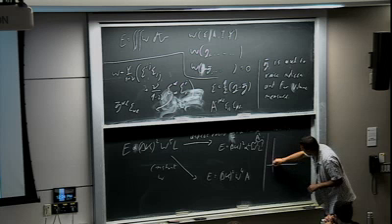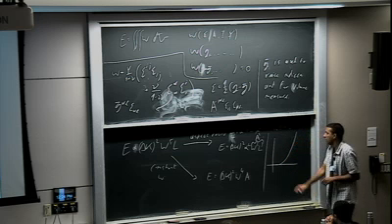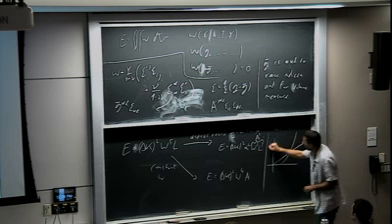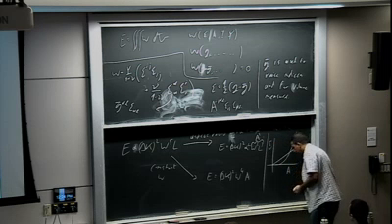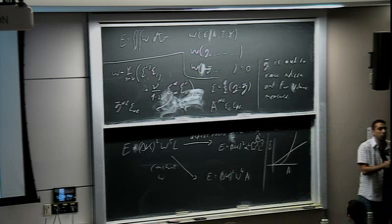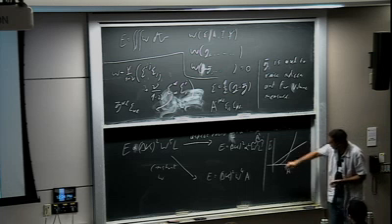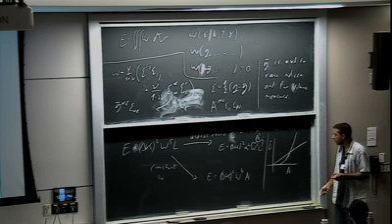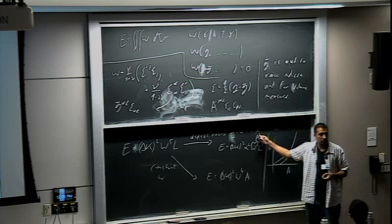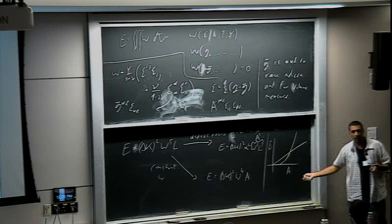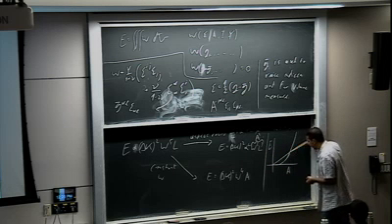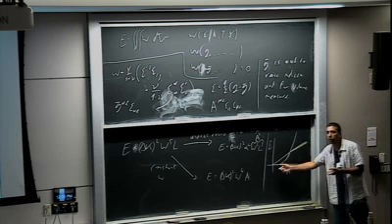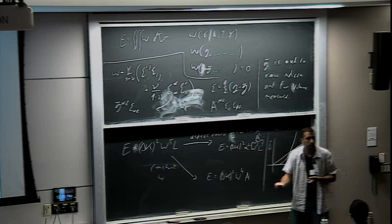This grows as area to the 3rd, so it starts very flat and it goes this way. And this begins as area to the 1st power. And this is elastic energy, and this is area. When we first nucleate these things, which are very, very frustrated, they will grow isotropically with a constant aspect ratio. And then they will hit a boundary, some length scale or some area scale, after which they would like to form something which is narrow along one of the directions. So this is a filamentation process which is driven solely by frustration.